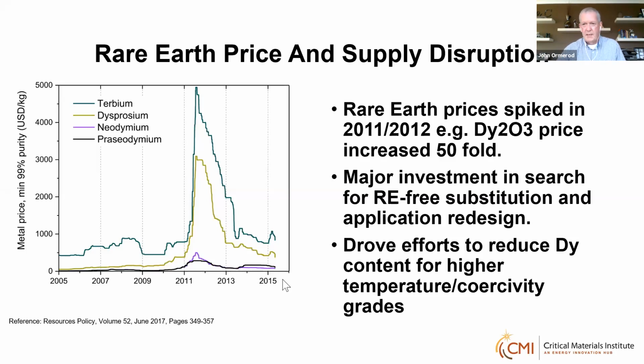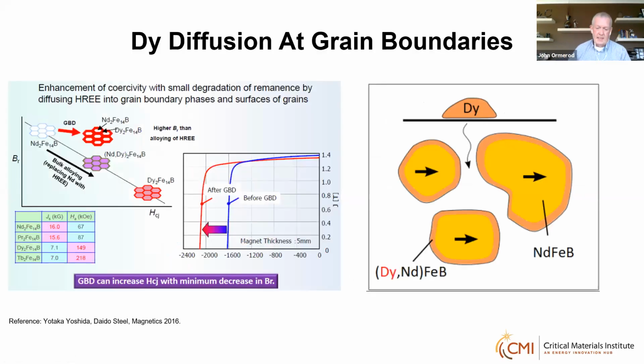And one of the things that happened was that several major magnet producers developed essentially the same approach, or at least similar approaches, by using processes that enrich the grain boundaries of the main Nd2Fe14B phase with dysprosium. And they used a variety of solid state, gaseous, and other forms of diffusion technologies. Now, it makes sense because the coercivity mechanism in the 2-14-1 based materials is determined by the grain boundary regions. So in a sense, the dysprosium within the grains isn't really contributing to the coercivity.